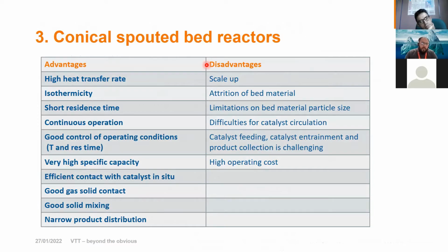there is high heat transfer rate. The temperature is uniform. The residence time can be very short, and it can be changed depending on the fluidizing velocity you choose. It can be used in continuous operation, and this type of reactor has good control on the operating conditions. You can use it with catalyst, and I already told you that there is a good contact between solid and gas.